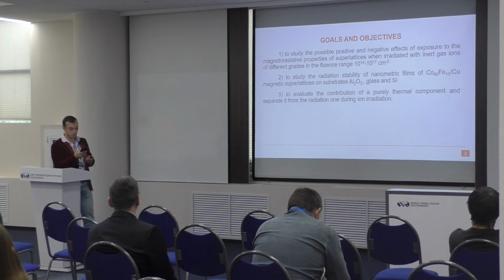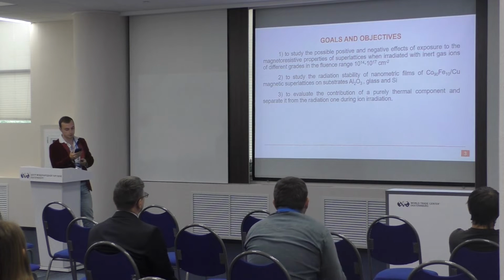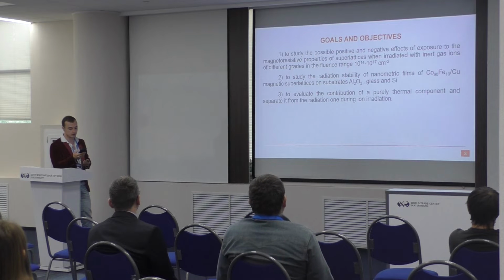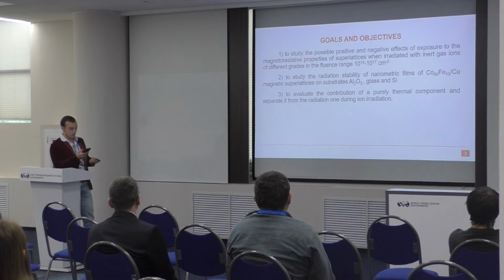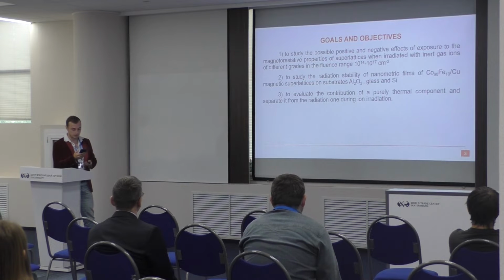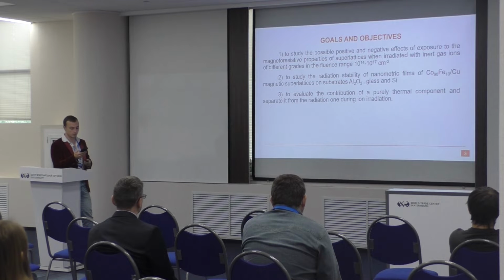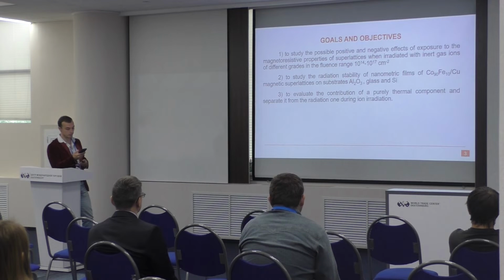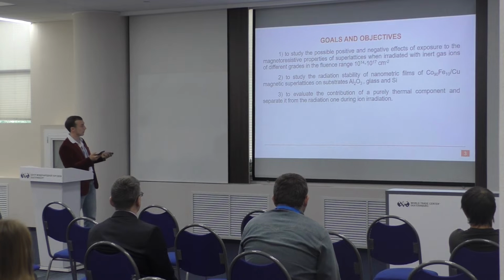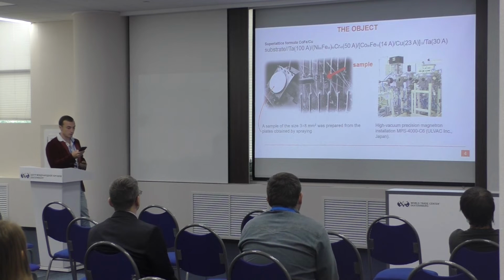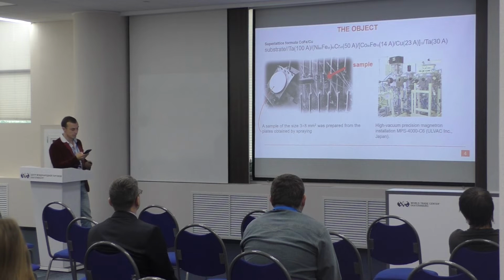The second goal is to study the radiation stability of nanometric films of cobalt, iron, copper magnetic superlattices on substrates of monocrystalline sapphire glass and monocrystalline silicon. The third goal is to evaluate the contribution of the purely thermal component and separate it from the radiation one during irradiation. The object of our research was chosen as the currently most promising superlattices, cobalt, iron, copper, which you can see